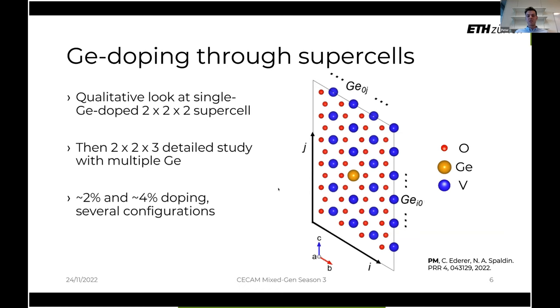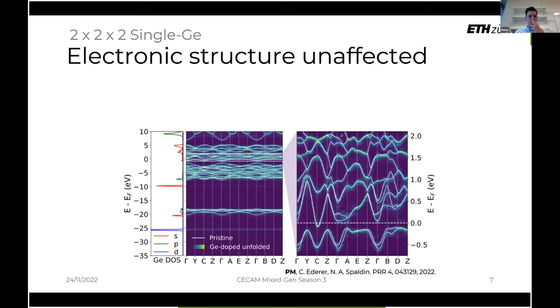So first things first, if we look at the smaller cell, we first want to note that the electronic structure, which I show here through the band structure, seems to remain unaffected.